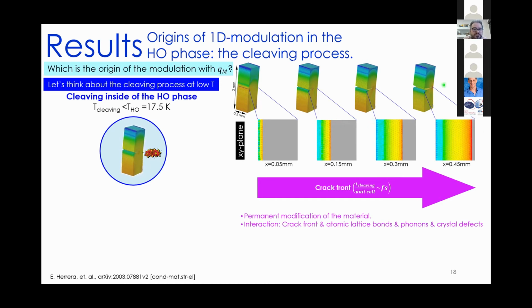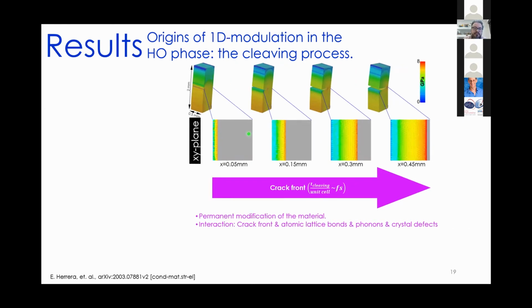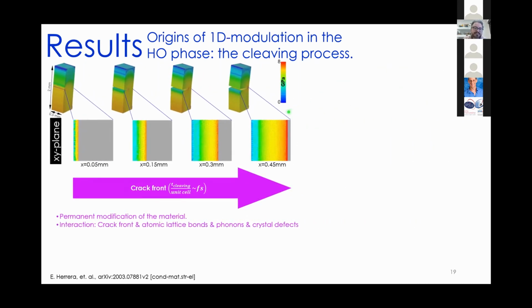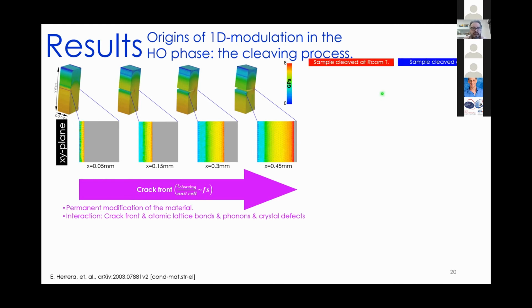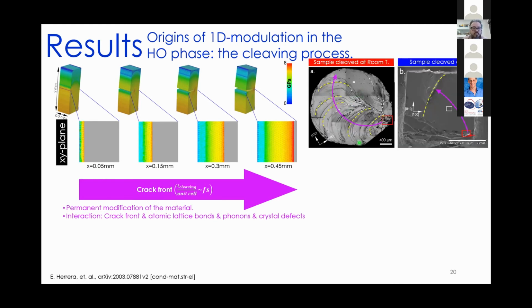Here we have the simulation of the cleaving process, showing how the pressure distribution changes on the crystal and also on the XY plane. As I said in previous slides, the propagation of the crack front during the cleaving leaves permanent modifications on the surface. So let's compare a sample cleaved at room temperature and another cleaved at lower temperature. Here we have the two examples.